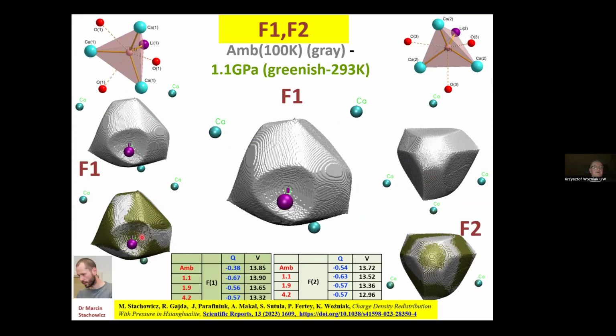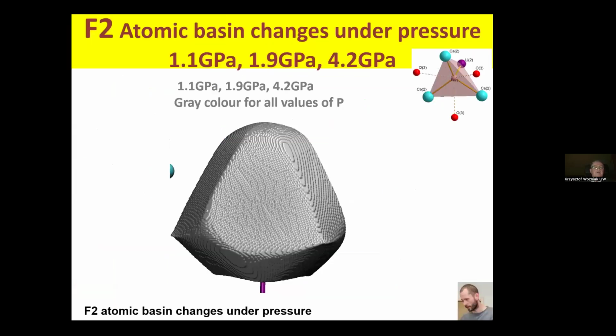And in these figures, with green patches, we have the projection of the atomic basin obtained at these thermodynamic conditions, meaning 1.1 gigapascal and 293 kelvins, onto the atomic basin obtained at ambient pressure and 100 K. So these green patches are showing us how electron density is somehow expanding when we are changing thermodynamic conditions. We can get charge, integrated charge, integrated volumes, and similar parameters.